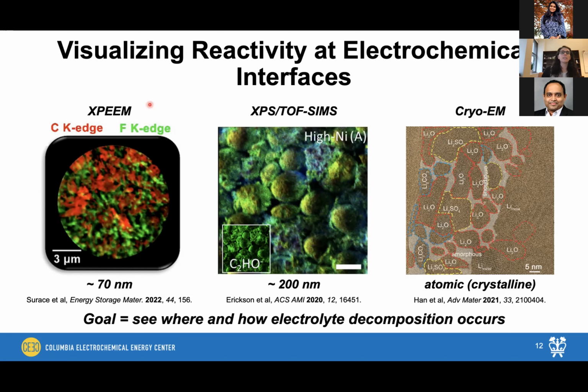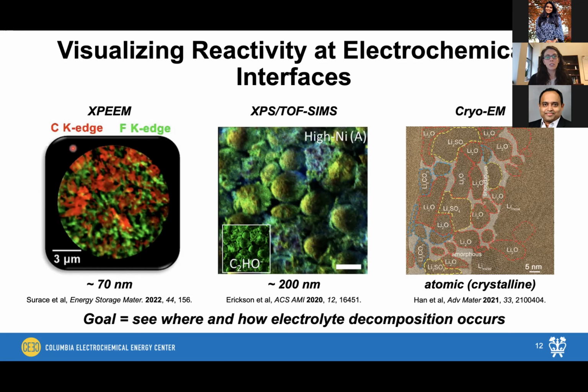So the first one here is X-ray photoemission electron microscopy. This is a synchrotron-based technique where we're essentially collecting spatially resolved X-ray absorption spectra. What you're looking at here is the C K-edge shown in red, the F edge shown in green, and you can see that you get a spatial resolution on the order of about 70 nanometers. So we're talking tens of nanometers here. The active particles in these systems are usually on the order of 1 to 10 microns. So this is suitable to actually distinguish where you have electrolyte decomposition on the composite, whether it's on the active particle or the carbon additives.